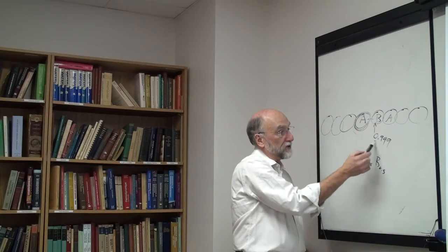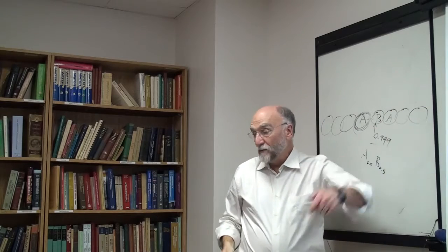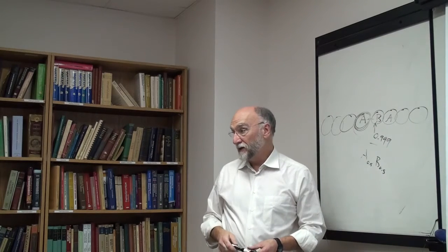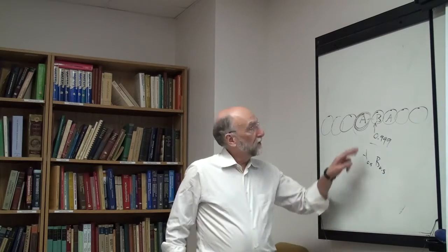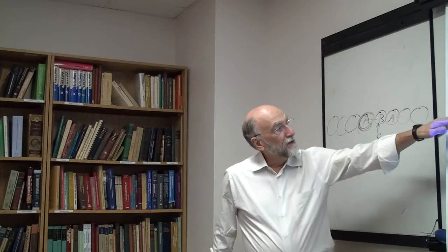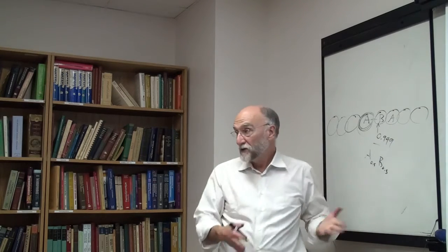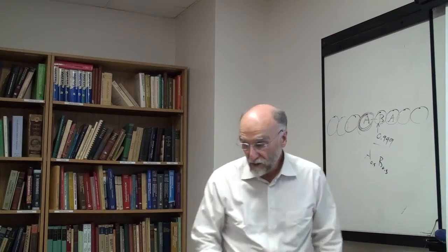But of course, this disorder adds up, and after you get out to 10 or 20 atoms, it's becoming basically disordered. So if you have an A here and you're considering an atom that's 25 distances away, what's the probability that it's a B? It's the mole fraction of B. There's no long-range order. That's short-range order.